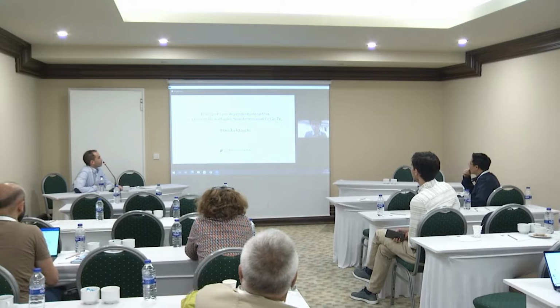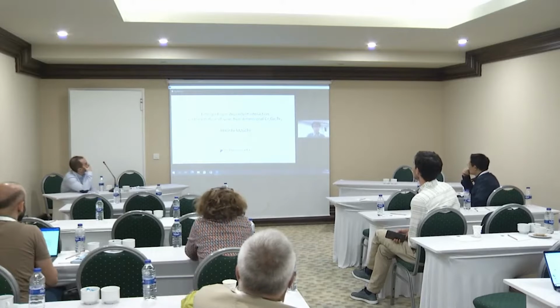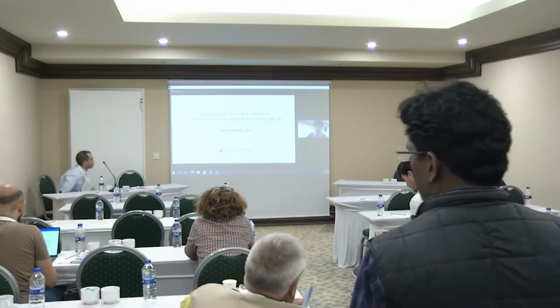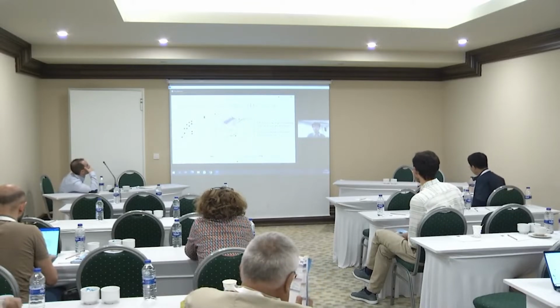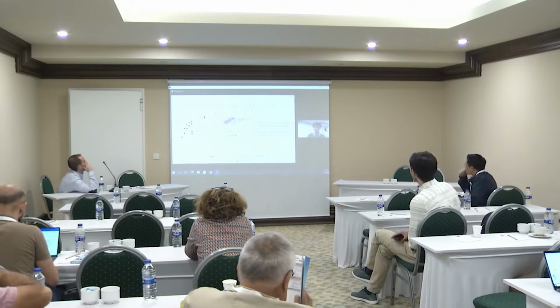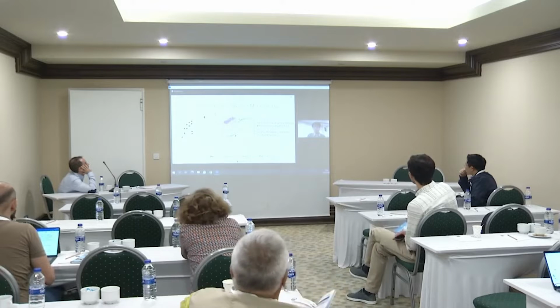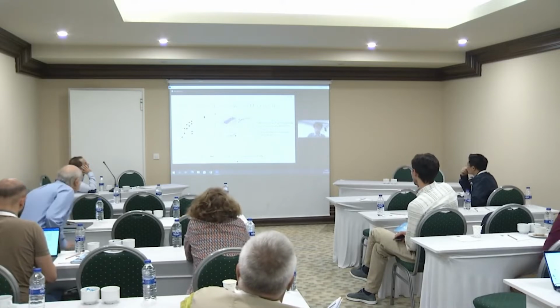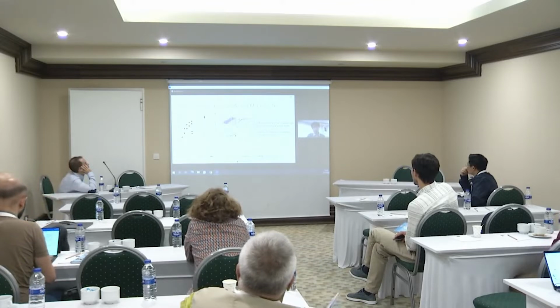I think most of you are familiar with 2D materials, and I know other invited speakers introduced them very nicely. So I will focus more on this 2D ferromagnet, chromium germanium tellurides. In atomically thin 2D van der Waals materials, chromium germanium tellurides is one of the prototypical materials. It was reported in 2017. A key feature is that we can cleave down to the atomically thin limit while keeping ferromagnetic behavior with high crystallinity. This is the number of layers versus Curie temperature, and this is the MH curve measured by MOKE.